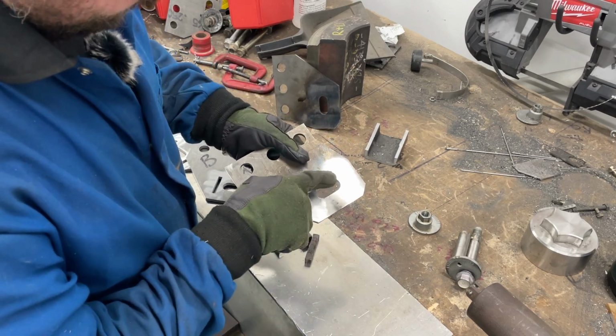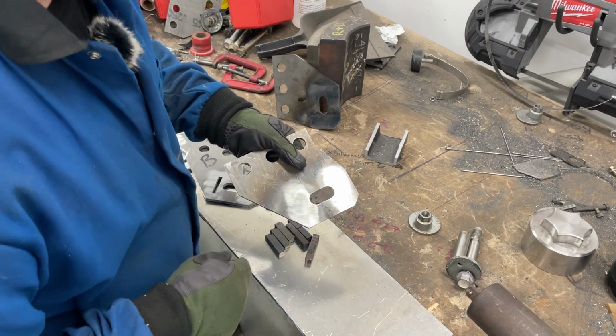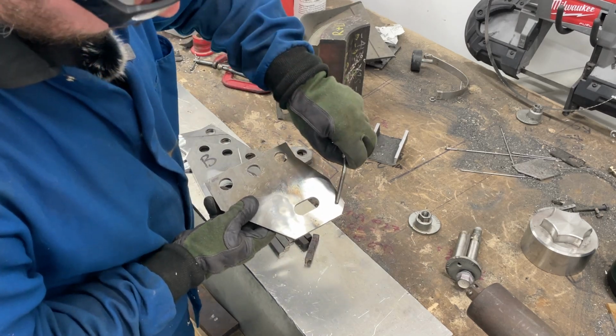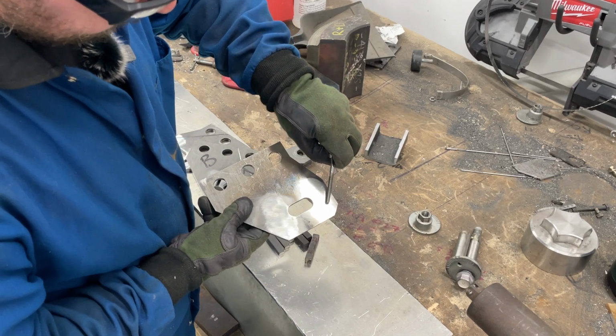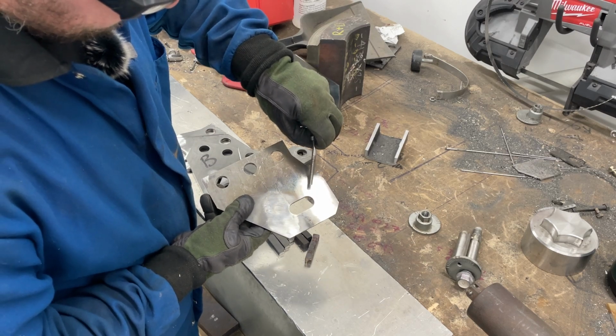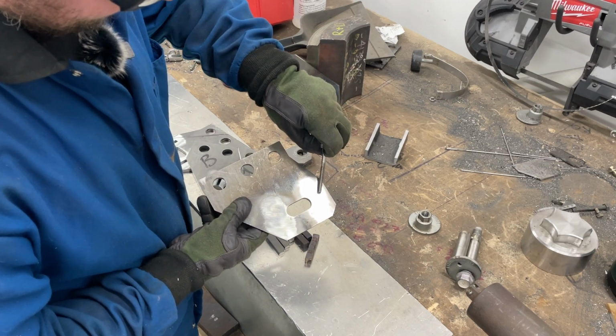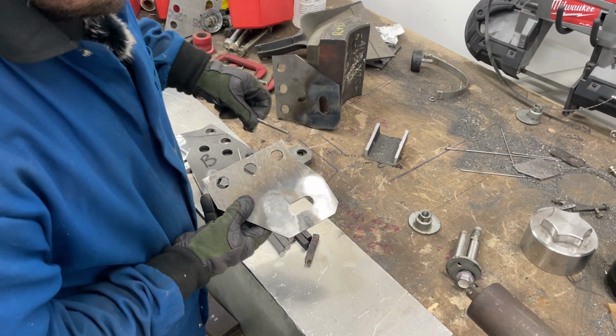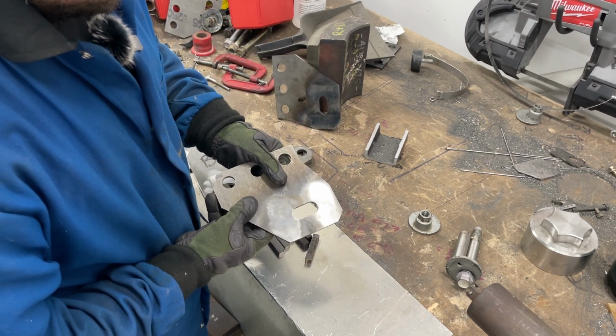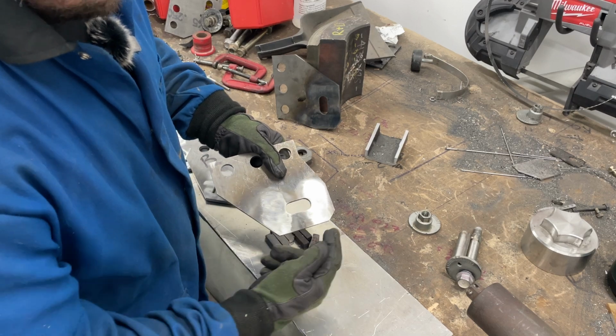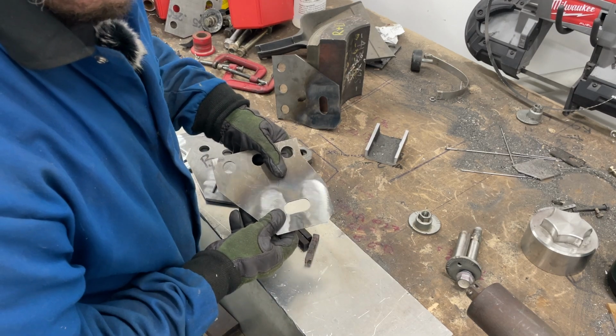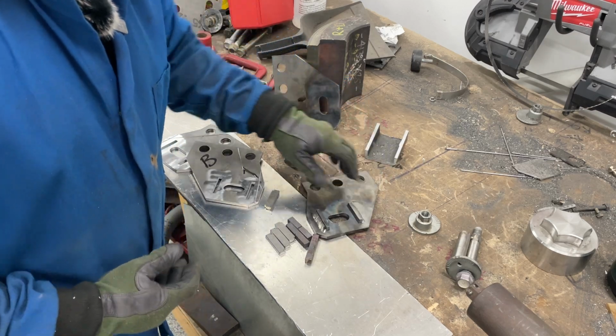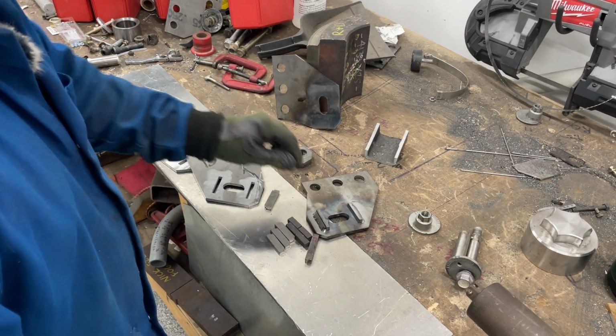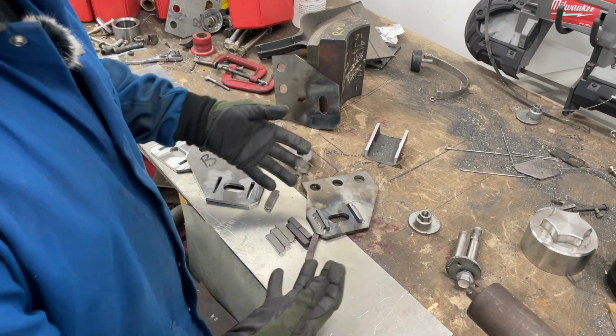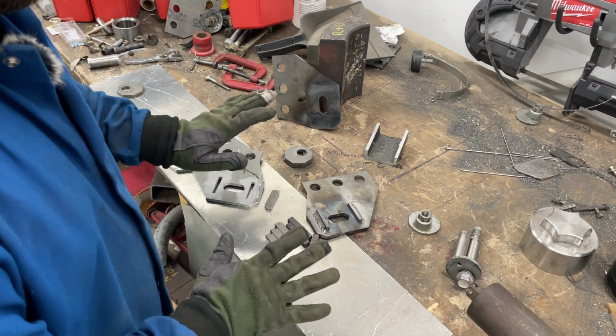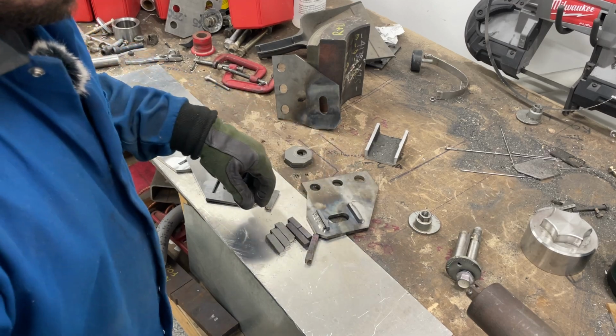Actually, in the grinding here, if you look really closely in the light, you're going to see a tiny, tiny line going around about a 1/2 inch wide, and that is near either the fusion line, where the weld metal touches base metal, or it's the heat affected zone, the area that's actually harder than everything else. Your stress relief will help reduce the hardness there, but really that stress relief is just trying to take off the most intense stress risers that are intrinsic to your material.